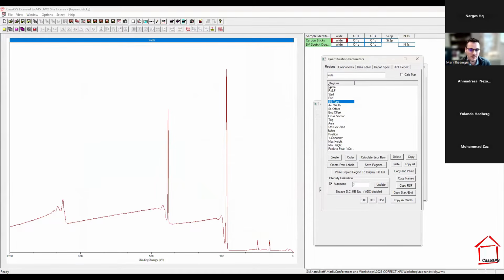So for insulating samples, and again I will talk about this a lot in the question period, as photoelectrons leave the surface of an insulating sample, that sample is going to build up a charge. If you don't compensate for that, your effective binding energy will start shifting. It'll start moving upwards until it finally disappears and you don't get any signal at all. To fix that, what we normally do for insulating samples is hit that surface with a flood gun of electrons, or sometimes charged ions, to compensate for that charge, and it'll reach a steady state.